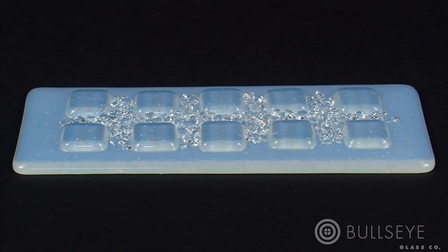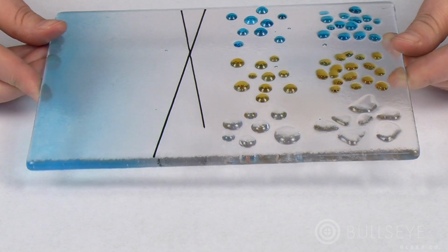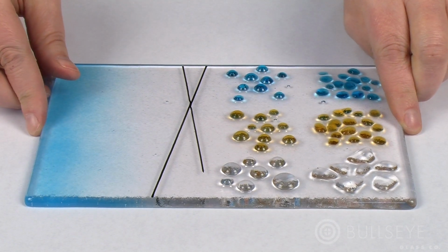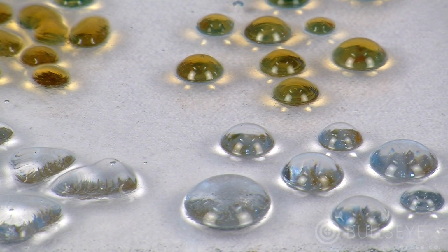In this piece, sheet glass design elements were tack-fused to 1425. Then frit was added before an additional firing to 1325. Note that light applications of fine glass, such as powder and fine-line stringer, will soften and flatten at the hotter end of this temperature range. Coarser frits and larger materials will remain in higher relief.